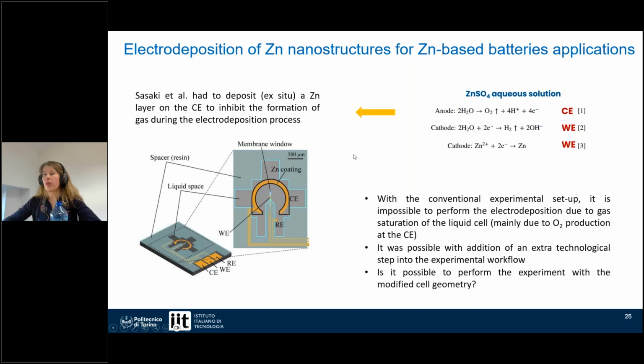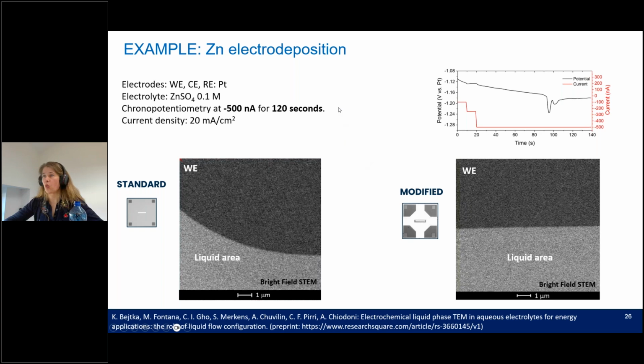They wanted to study the zinc electrodeposition, and to be able to do this, they deposited the zinc layer on the counter electrode to inhibit the production of the gas during the electrodeposition. So they then were able to perform and study the electrodeposition process, which was of their interest. However, with addition of the extra technological step, which was prepared ad hoc for this experiment. So we wanted to see if having this improved liquid flow configuration can help and make it possible to perform this experiment without incorporation of this technological step. And this is what actually I will show now.